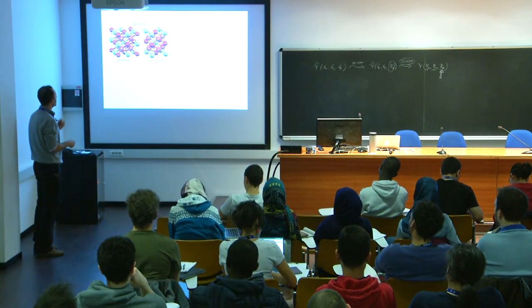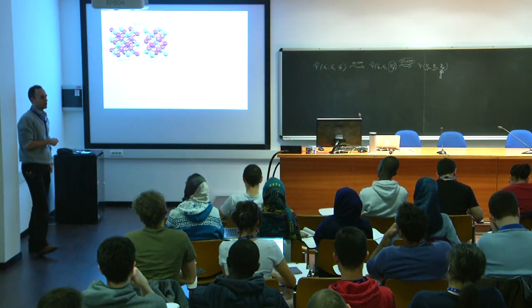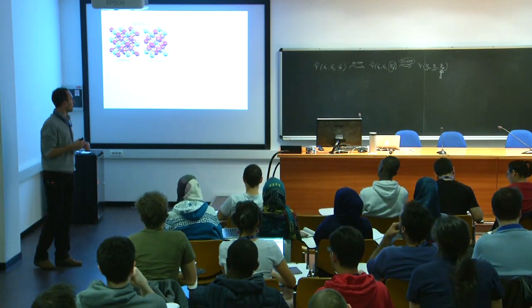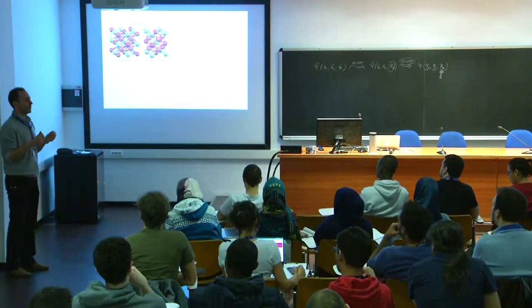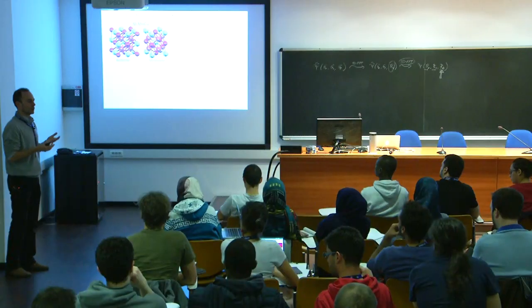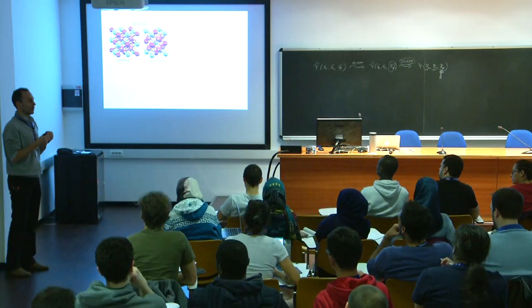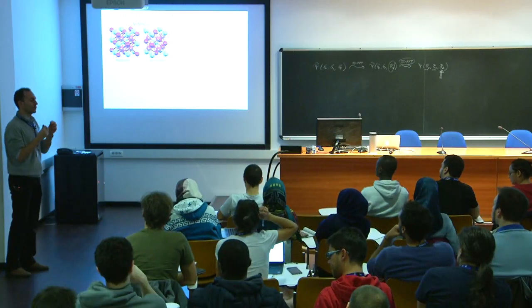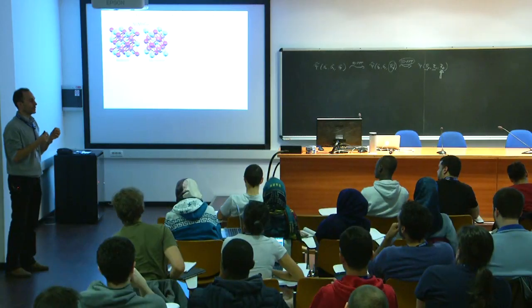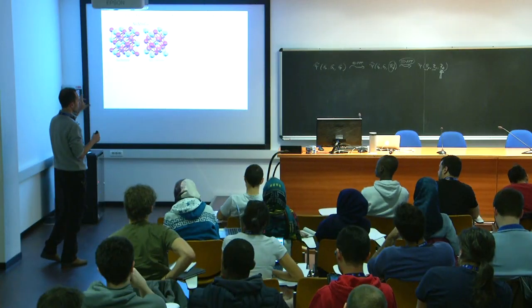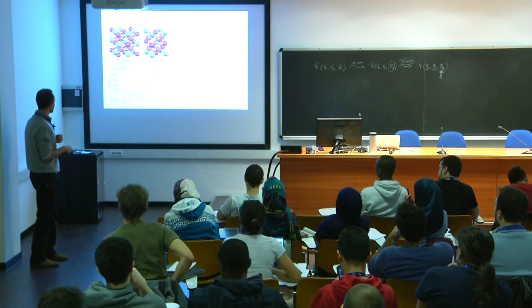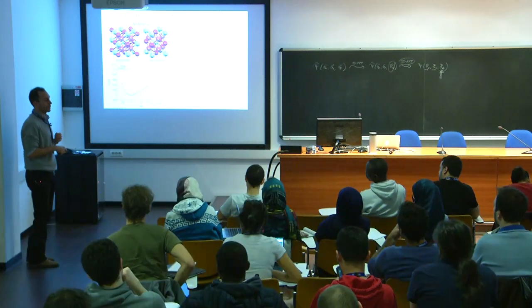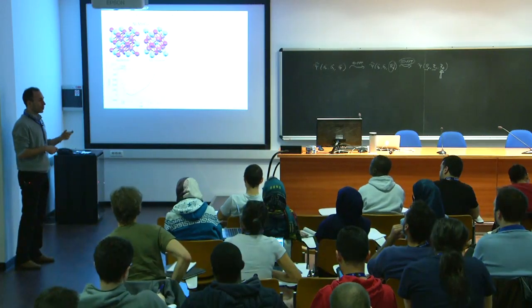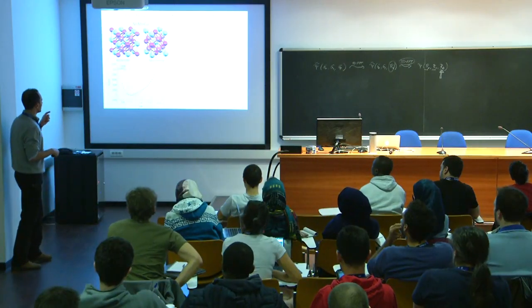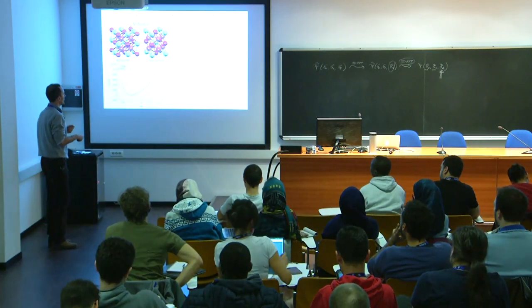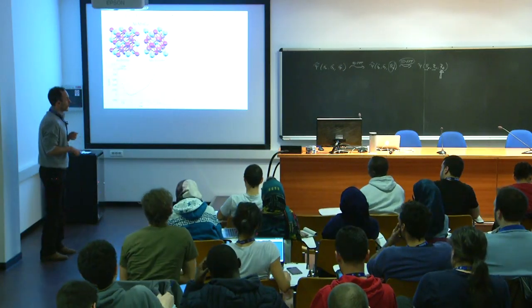However, the energetics is very delicate, so these two phases are very close in energy. If you compromise the description of magnetic interaction between manganese, you may end up with the wrong ordering. Because of these two energies being close to each other, the part of the energy relating to the magnetic interaction between manganese is very important, and if you get that wrong, you might get the wrong order, and in fact that's the case. DFT+U corrects that because of the better localization, lowers the magnetic interaction between manganese ions, and corrects the relative stability of the two phases.